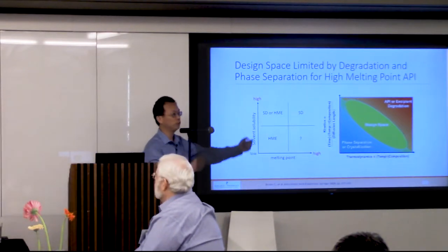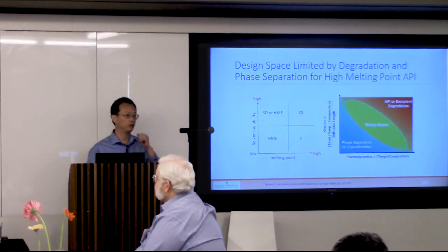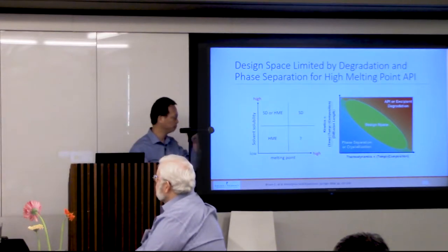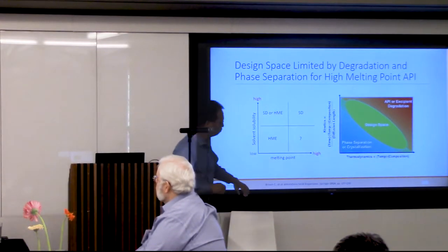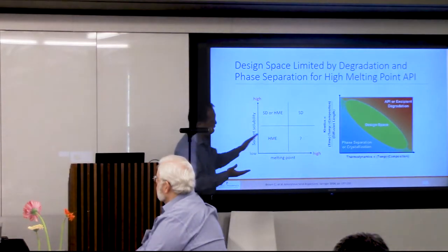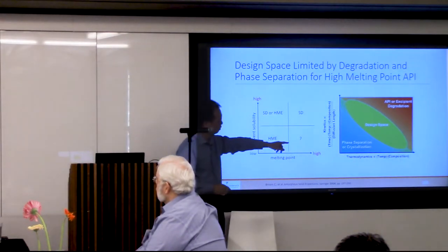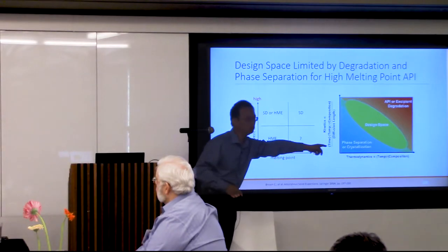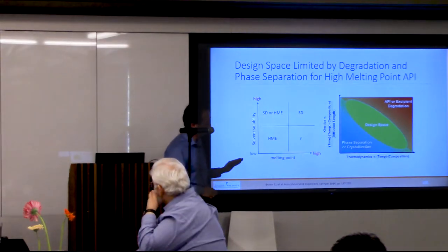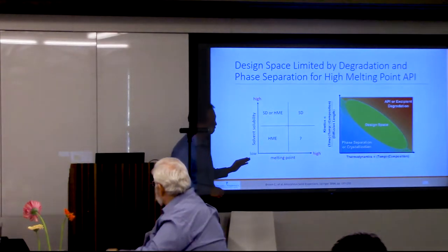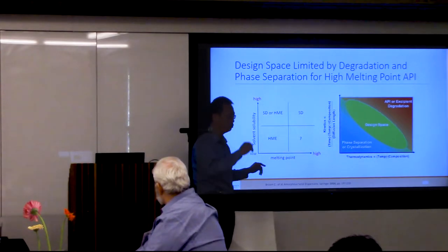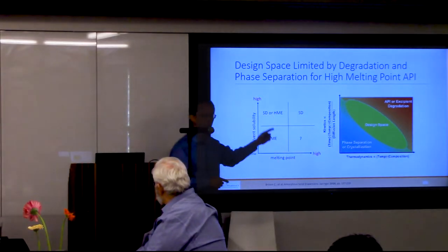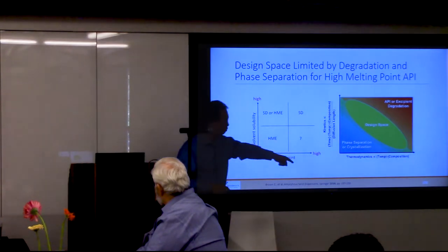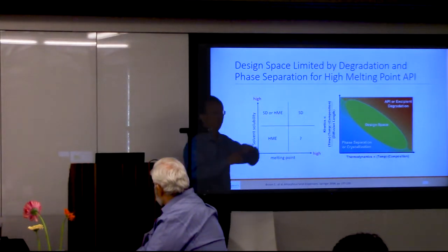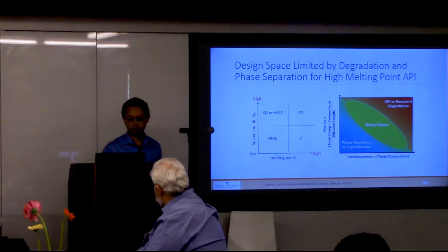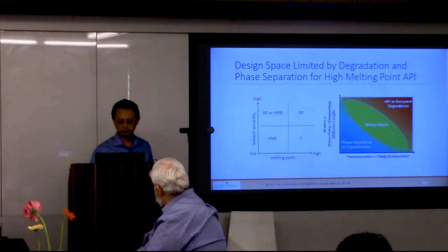Okay. But then this dissolution process takes time. It depends on the screw design, depends on how you mix them, depends on the drug loading. So if you don't have high enough temperature, and also you don't have high enough mixing, the drug is still crystalline. So to make a solid dispersion using an extrusion process, you have to increase the temperature and also give extensive mixing. That's how you actually dissolve the drug in the polymer. But if you go too far, the drug will degrade, right? So there's a window, there's a design space.